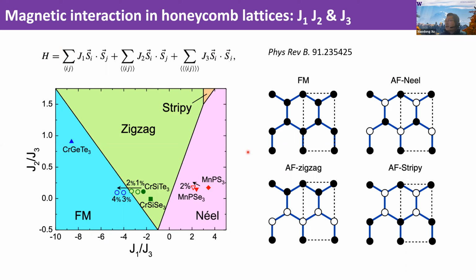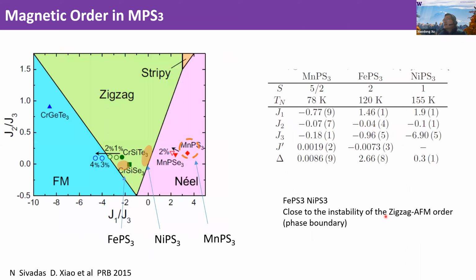And in this little corner, you can also get a stripy order. Basically the spin is aligned along these armchair directions, but aligned oppositely in the adjacent armchairs. So for this MPX3 family of materials, they actually have a pretty rich magnetic order. For example, iron phosphotrisulfide and nickel phosphotrisulfide belong to these zigzag antiferromagnetic orders. And for manganese phosphotrisulfide, actually it's a Néel order.